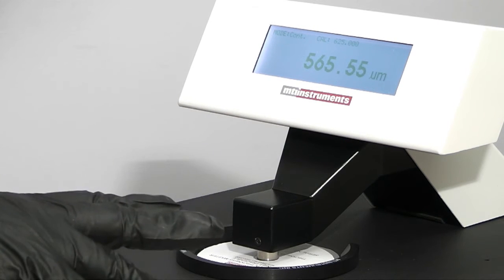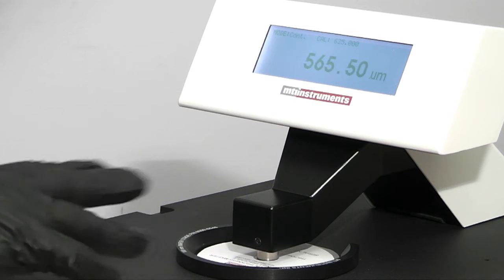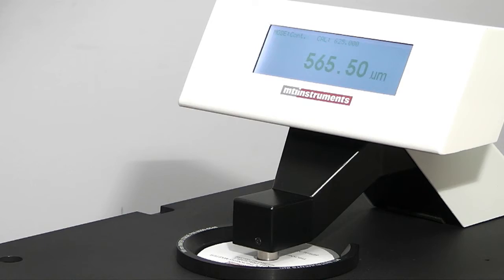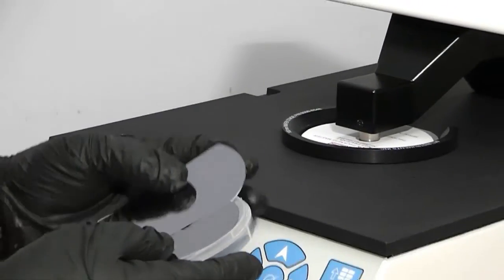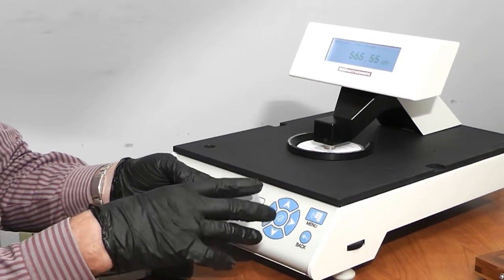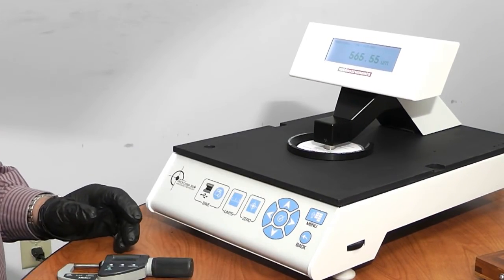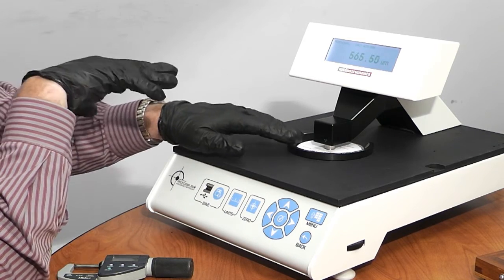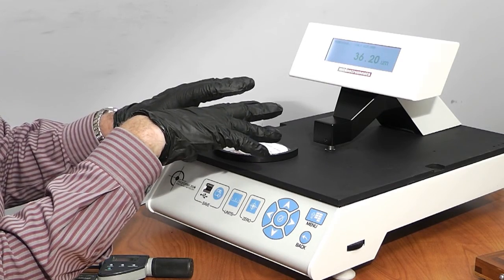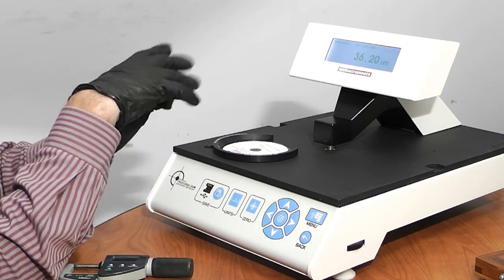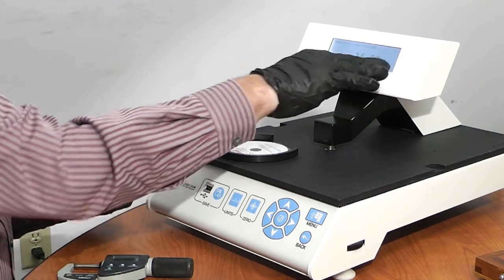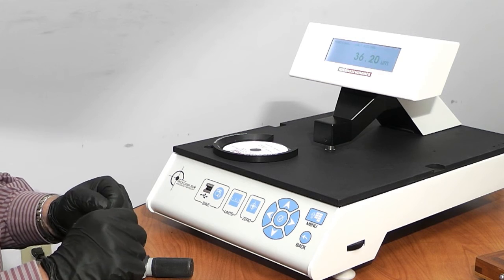And you don't need to recalibrate for any other conductive wafers. One calibration on a low conductivity wafers is good. But with high bulk resistivity wafers, if the process changes or you're measuring a different bulk resistivity or a different process, you do need to calibrate on a known wafer standard, whereas you don't with silicon. But again, you have to keep in mind that when you don't have anything in the gap, you're going to be getting this false reading. So the only downside to this is you've got to just learn to ignore the reading. You don't get the three dashes that nothing's in the gap anymore. Thank you.